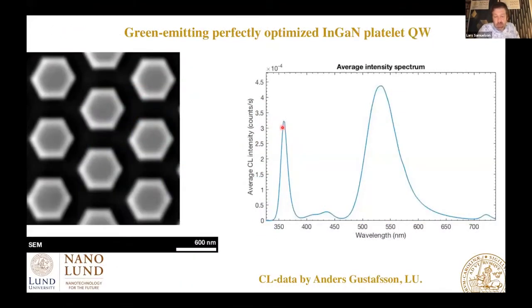So what you can see here is the peak from the gallium nitride. This is 355 or so nanometers. Here's the emission from the template material around 440 or so. And here's the emission, in this case, from a green quantum wells grown on these platelets that you see over here.